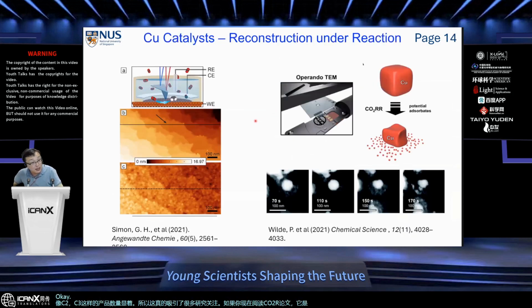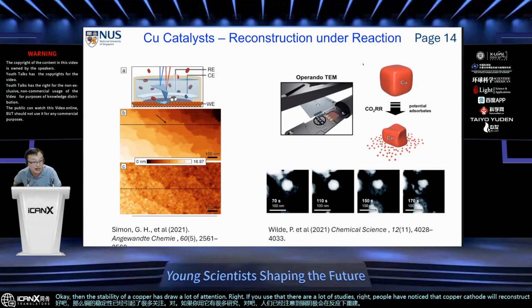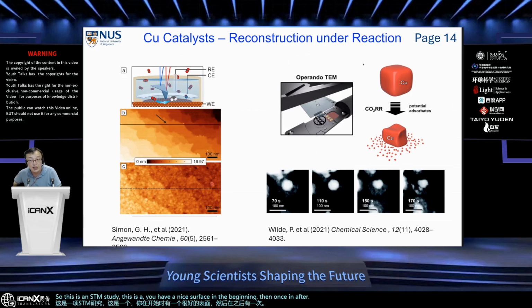Okay, then the stability of copper has to draw a lot of attention, right? There are a lot of studies, right? People have noticed that copper catalyst will reconstruct under the reaction conditions. So this is an STM study. You have a nice surface in the beginning, then after the reaction for a little while, the catalyst surface looks like this. People also study using the in situ TEM process, which we're probably going to hear more about in the next talk. People find that if you have a particle in the beginning, then the particle will sort of disintegrate.